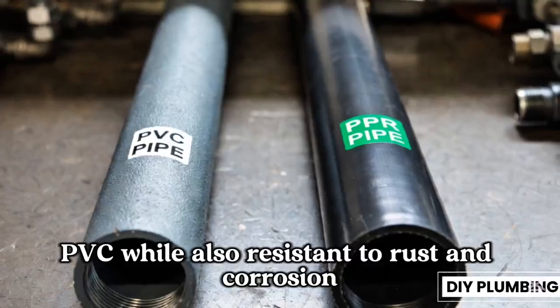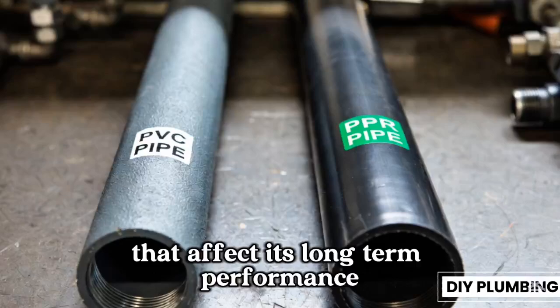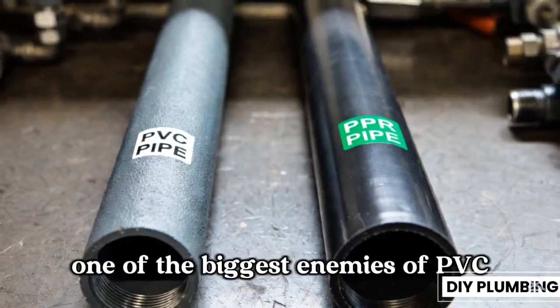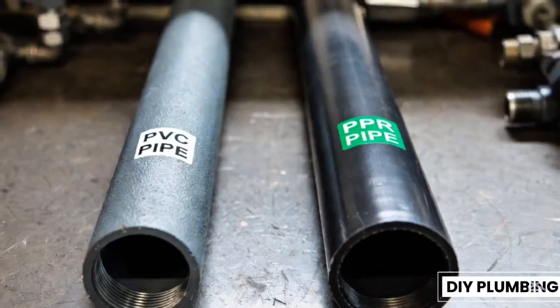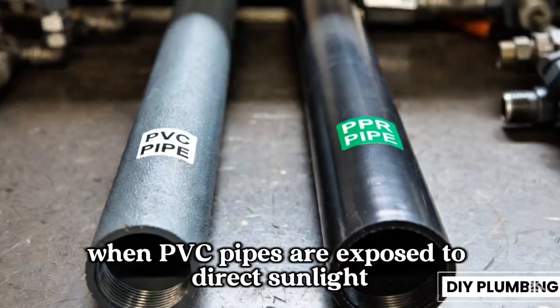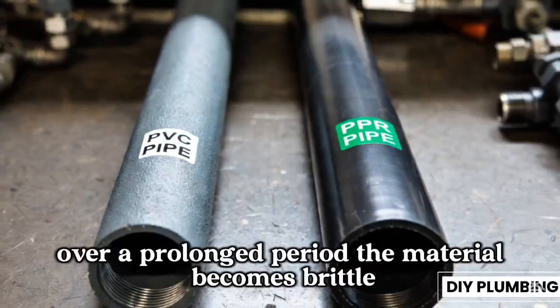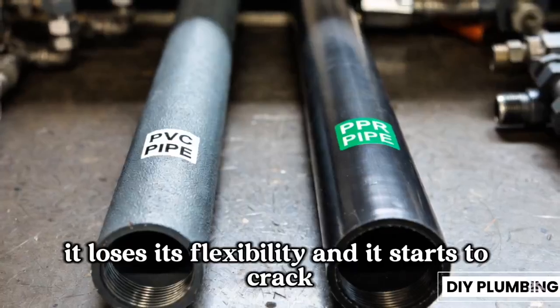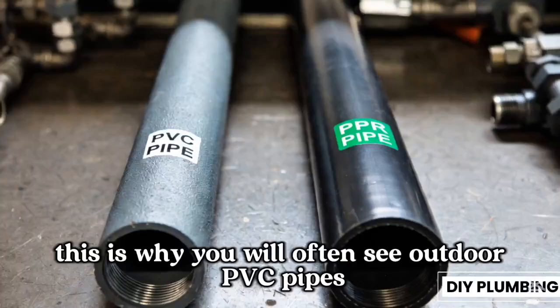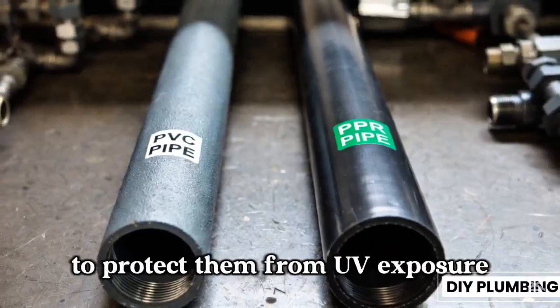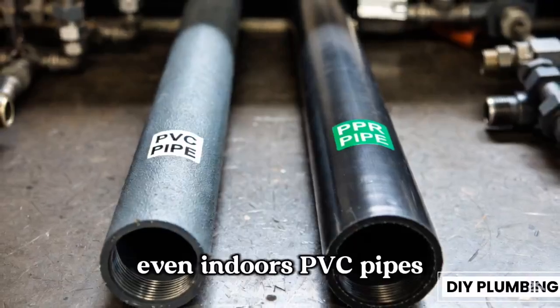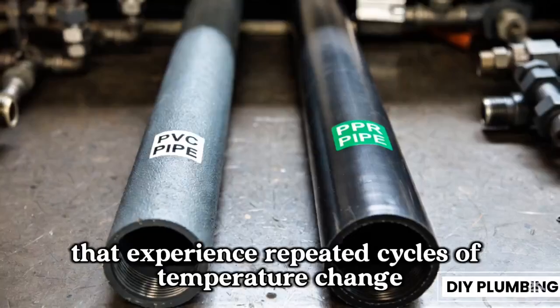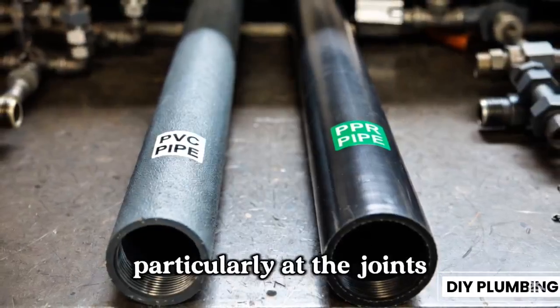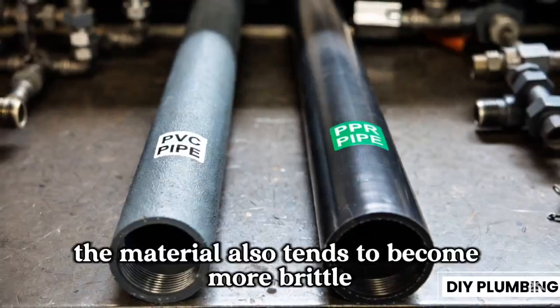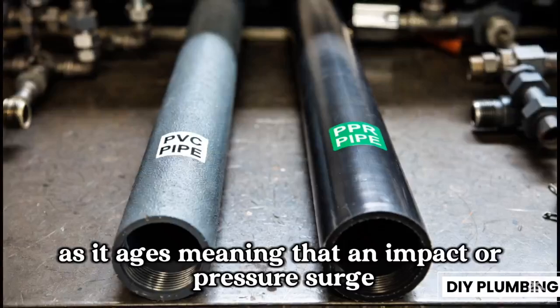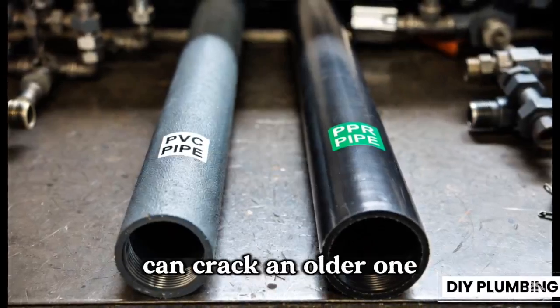PVC, while also resistant to rust and corrosion, has some weaknesses that affect its long-term performance. One of the biggest enemies of PVC is ultraviolet radiation from the sun. When PVC pipes are exposed to direct sunlight over a prolonged period, the material becomes brittle, it loses its flexibility, and it starts to crack. This is why you will often see outdoor PVC pipes that have been painted or wrapped to protect them from UV exposure. Even indoors, PVC pipes that experience repeated cycles of temperature change can develop micro cracks over time, particularly at the joints. The material also tends to become more brittle as it ages, meaning that an impact or pressure surge that would not cause any problem in a newer pipe can crack an older one.